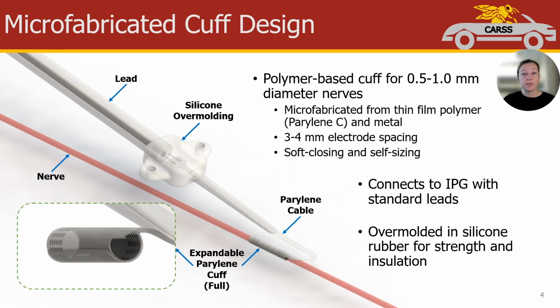For these reasons, we developed this microfabricated cuff electrode. The cuff and cable portions are built from thin film Parylene C and thin film metal. The cuff is then wrapped around the nerve in a spiral configuration with the exposed electrodes on the inner surface of the cuff. The cuff is sized to be either 0.5 or 0.7 millimeters in diameter, but because of the flexible nature of the thin film Parylene, it can be expanded, fit around the nerve, and will gently self-size to the diameter of the nerve.